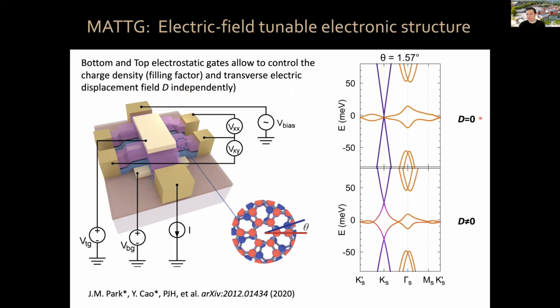Okay, and the electronic structure: these two, the monolayer-like band and the magic angle bilayer-like band, are orthogonal, uncoupled. But if you apply a transverse electric field and you break the mirror symmetry, you couple them, okay? So this is the electronic structure in the presence of a finite displacement field. As you can see, this Dirac crossing lifts and splits like that, yeah? Now, let me start showing you some data.